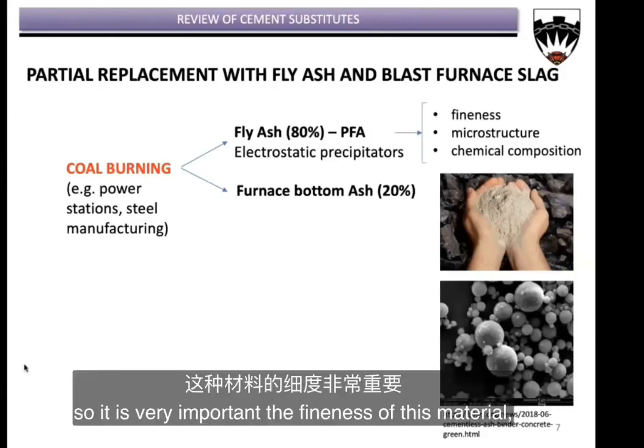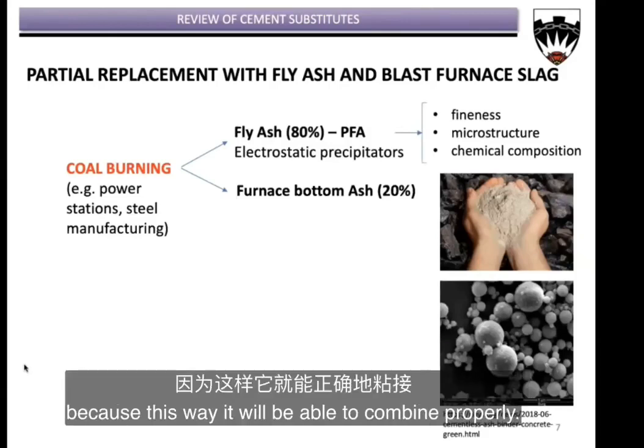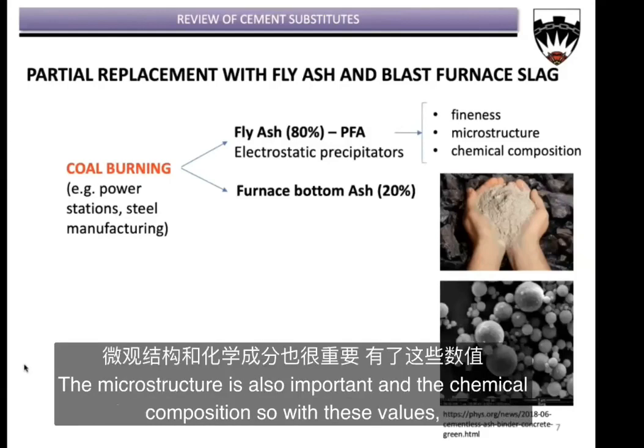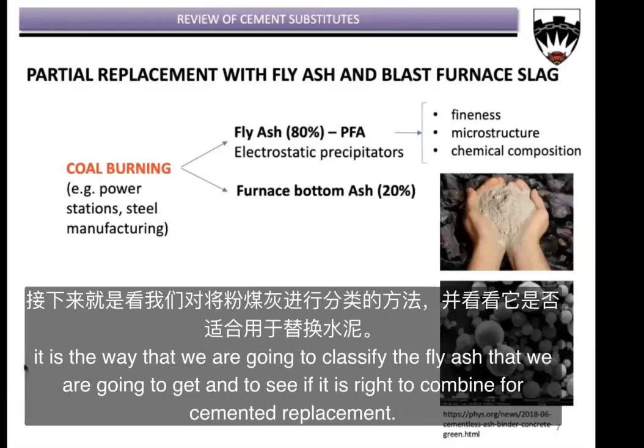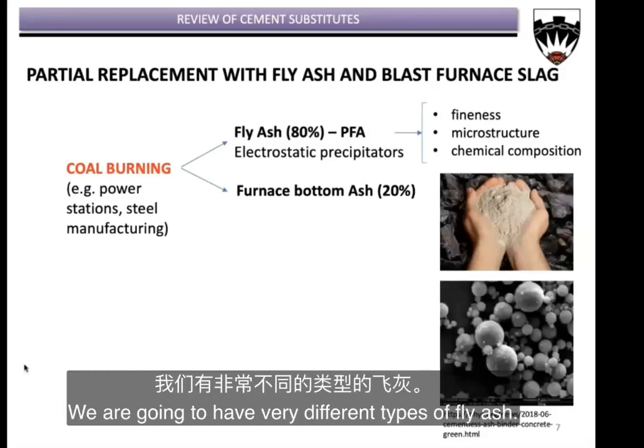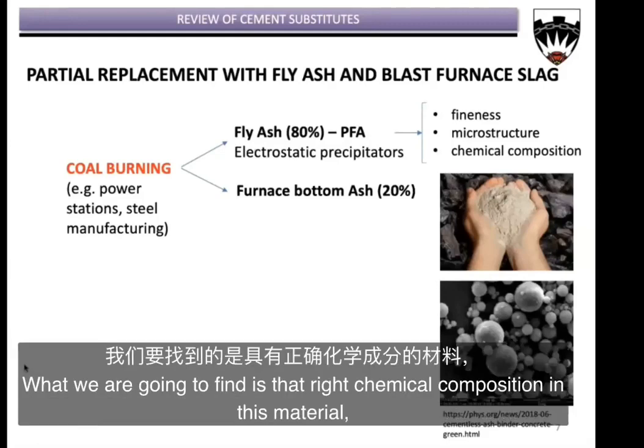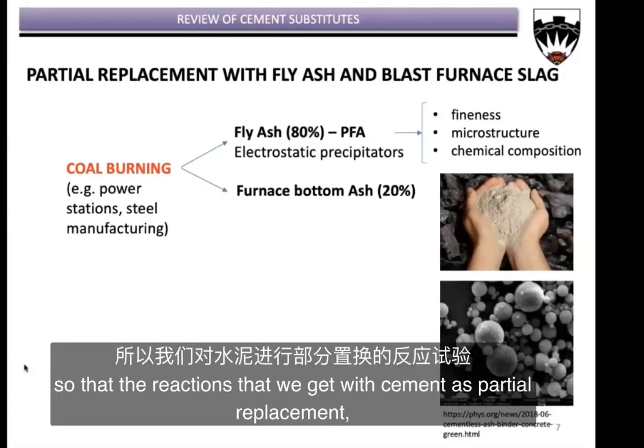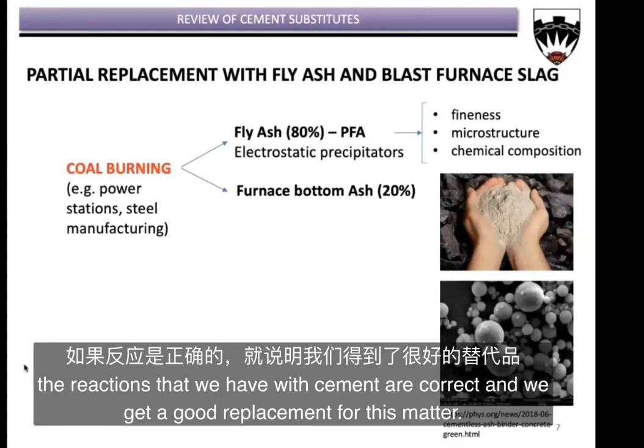So the characteristic that we need for this fly ash is mainly fineness. It is very important, the fineness of this material, because this way it will be able to combine properly. The microstructure is also important, and the chemical composition. With these values, we are going to classify the fly ash that we get, and see if it is right to combine for a cement replacement. We are going to have very different types of fly ash. What we are going to look for is the right chemical composition in this material so that the reactions we get with cement as partial replacement are correct, and we get a good replacement for this material.